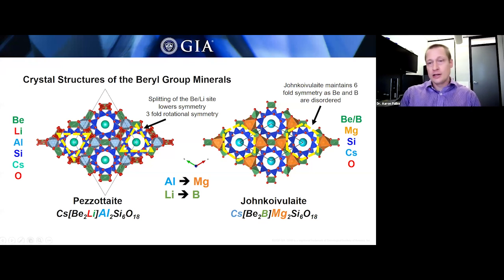So in johnkoivulaite and other members of the beryl group, we have this 6-fold rotational symmetry within those silica rings, where you can see that you could rotate the crystal structure 6 times until you get back into the original orientation. And each time you rotated it, you would have the same crystal structure. You would be looking at essentially the same crystal lattice. With Pezzottaite, because we're splitting those sites apart, we can only rotate the crystal structure 3 times before getting back to itself because some of those sites are split.